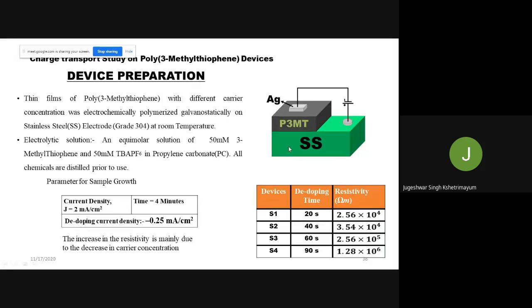The first one we retain. The others, S1 sample, S2 sample: once you make the film, we de-dope it and apply the reverse current for 20 seconds. In another sample, we apply the reverse current for 40 seconds. Another sample, 60 seconds. Another sample, 90 seconds. When we apply a reverse current, the polymer chain is not affected. The effect is on the amount of charge carriers, meaning the dopants. We are removing the dopants. How much we apply here is 0.25 milliampere per centimeter square. The plot time is 4 minutes. Then after, we are removing the dopants here.